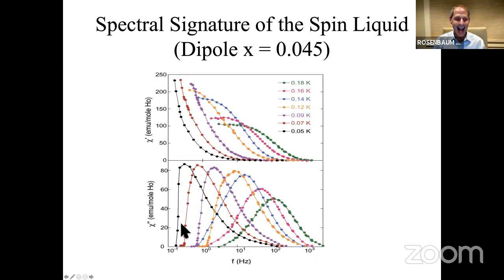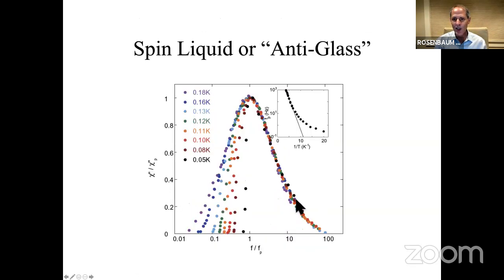The spectrum is narrowing, and I'm going to do the same trick. I'm going to look at the imaginary part of the susceptibility. I'm going to plot these on top of each other, normalizing by the peak frequency and the peak height. And so what you see here is those same curves coming on top of each other. And now, as I go from higher temperature, the purple, to the lower temperature, the 50 millikelvin, in fact, it almost looks like a gap opens up. The distribution, the spectrum narrows.